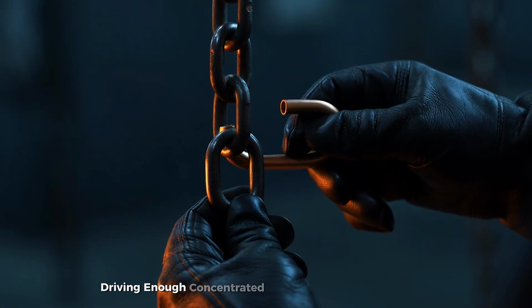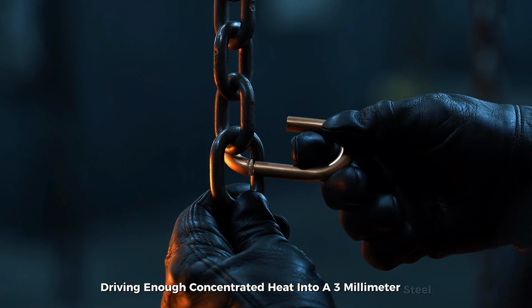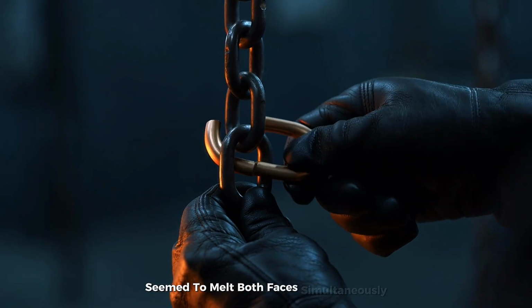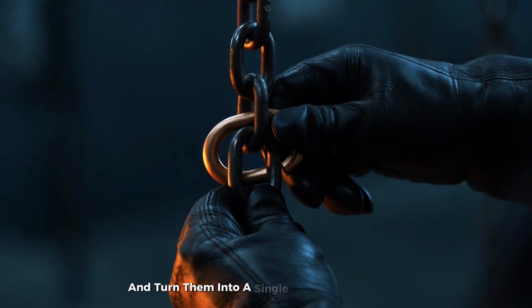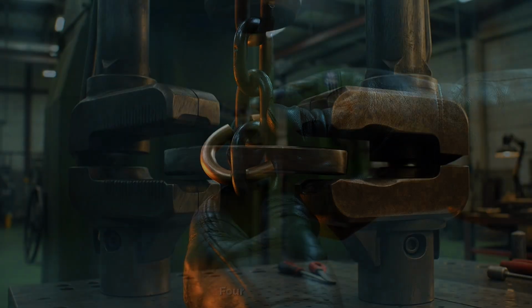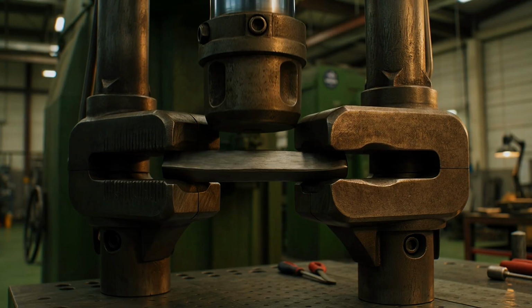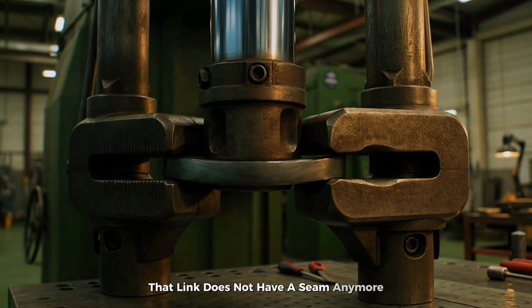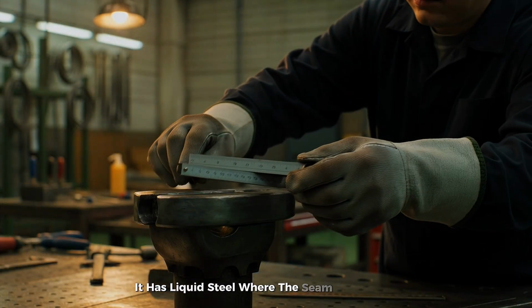Driving enough concentrated heat into a 3mm steel seam to melt both faces simultaneously and turn them into a single pool of liquid metal. For 0.3 seconds, that link does not have a seam anymore. It has liquid steel where the seam used to be.